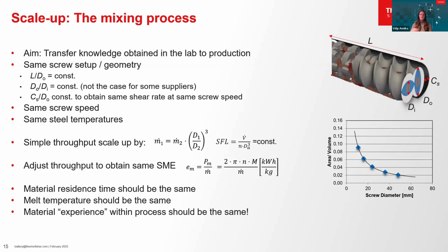However, in wet slurry processing, it is most often so low that keeping the specific feed load constant is usually sufficient. If you can measure the material residence time, it should remain the same to ensure similar processing conditions and material properties. The melt temperature should also be consistent between lab and production to maintain the same material thermal history. By adhering to these principles, the material's experience within the process should be the same, ensuring process consistency and maintaining product quality.